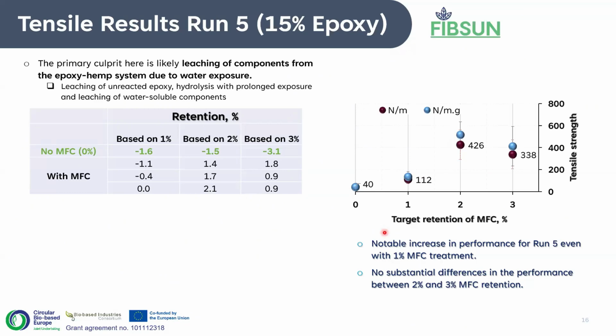So this for us is very crucial, because we see that despite the fact that we have very low performance compared to, say, the PP/PE binder, we are able to actually get towards the other binder type by incorporating MFC. And MFC works better with epoxy binder compared to PP/PE. And this is also good in this regard, because the other partner identifies this particular batch of non-woven to be the best for them to incorporate into the hybrid composite.